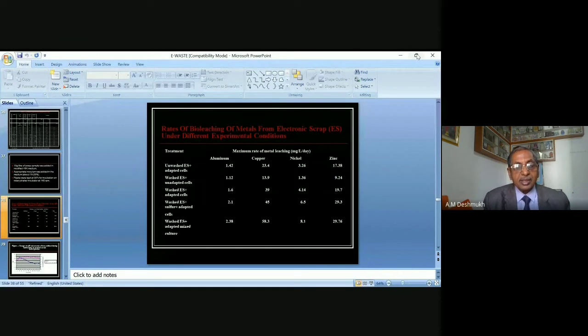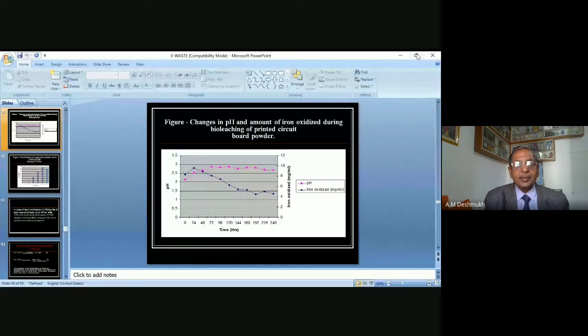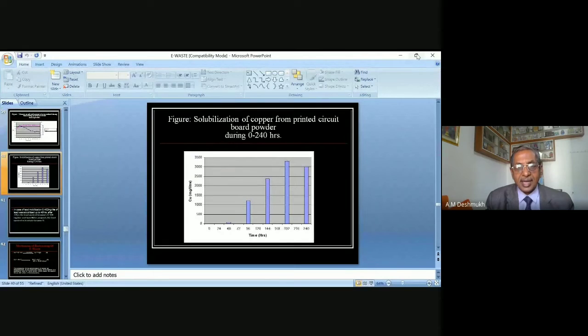So here, I'm not going into detail. Here we observed iron oxidizing bacteria in red color. They are increasing and the iron concentration is slowly decreasing. So the reduced iron is converted into oxidized iron. And we observe after a specific time solubilization of copper from printed circuit board powder. We studied copper first.